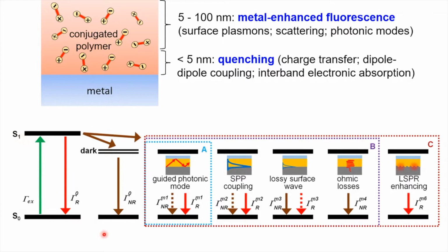What we found when we integrated metasurfaces with fluorescent conjugated polymer semiconductors, is that in addition to the regular absorption and emission transitions from singlet excitons in the semiconductor, we would get a portion of the fluorescence, or the transition from the S1 state, the first excited singlet state, going to either a dark mode, so in other words, it would be quenched, or they would couple to various photonic or plasmonic modes, or loss mechanisms of the metasurface. And the main ones we identified were either coupling to guided photonic modes. In general, this would cause an increase in the radiative rate, and or coupling to surface plasmon polaritons, and this also would tend to improve the radiative rate.